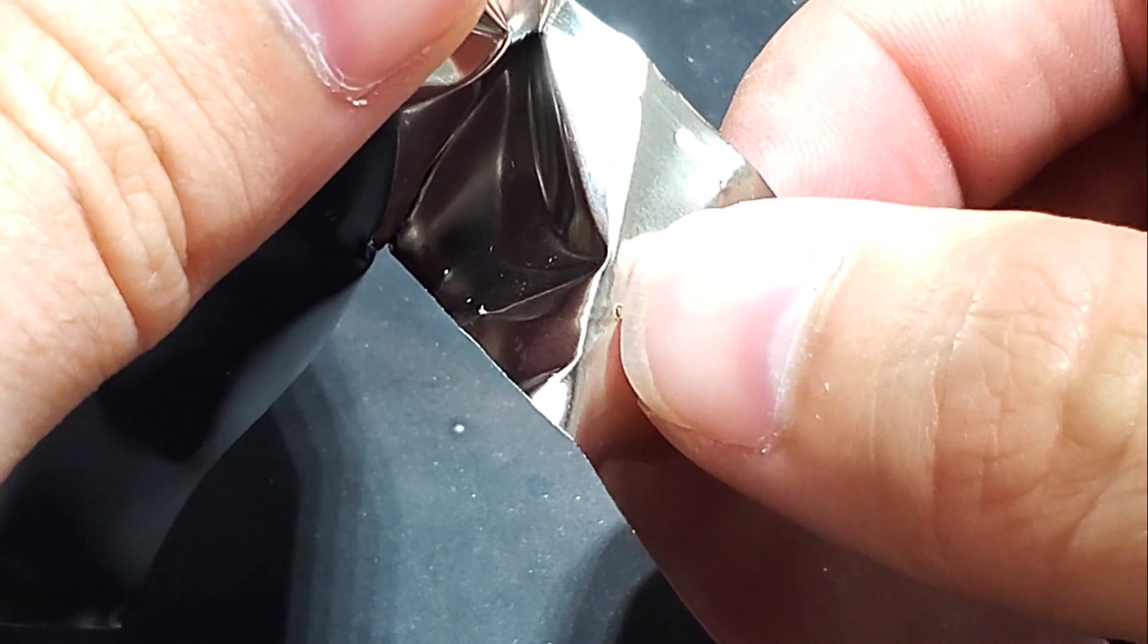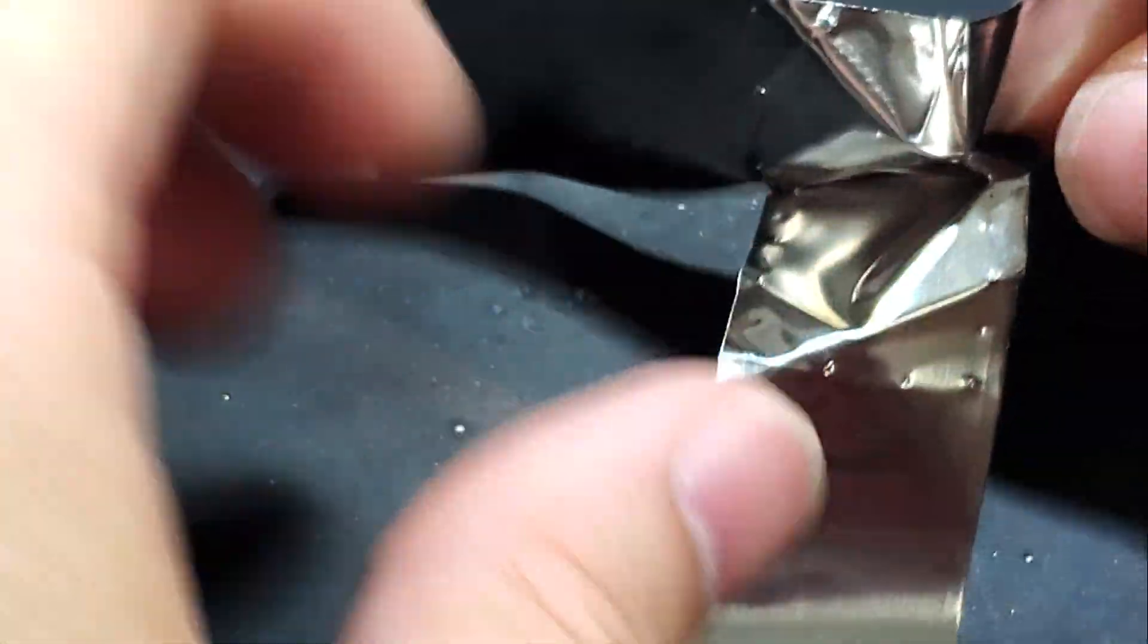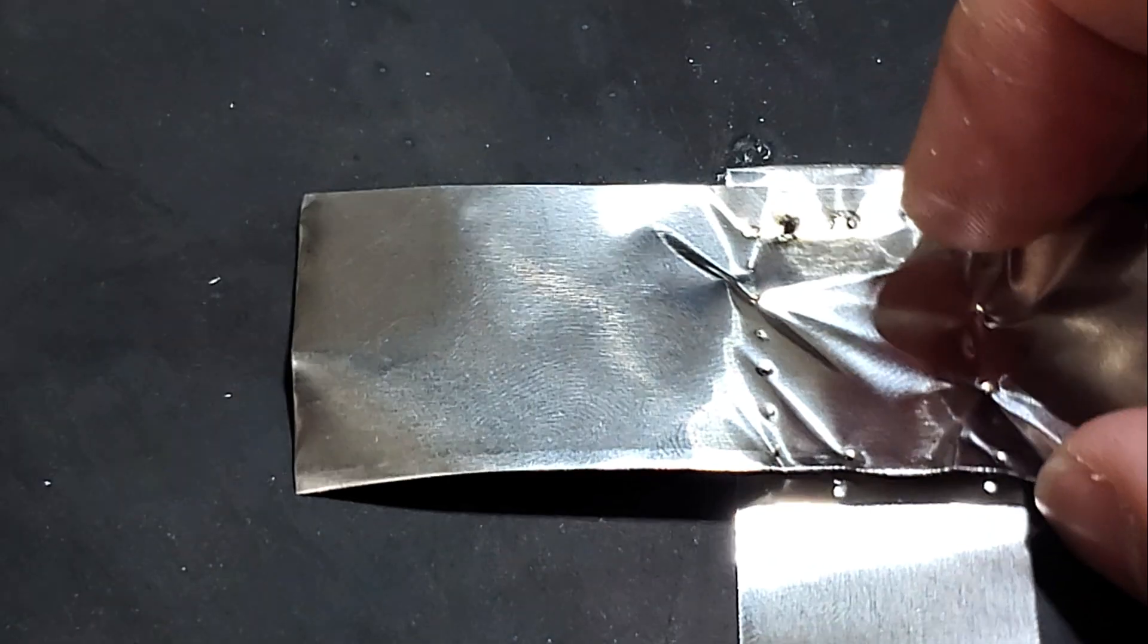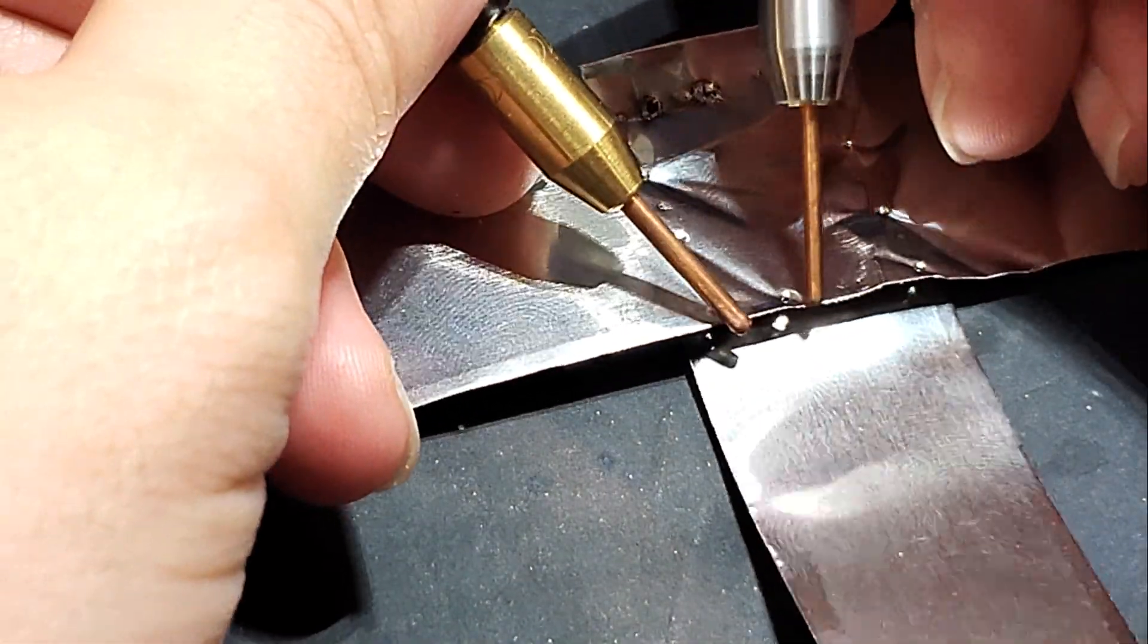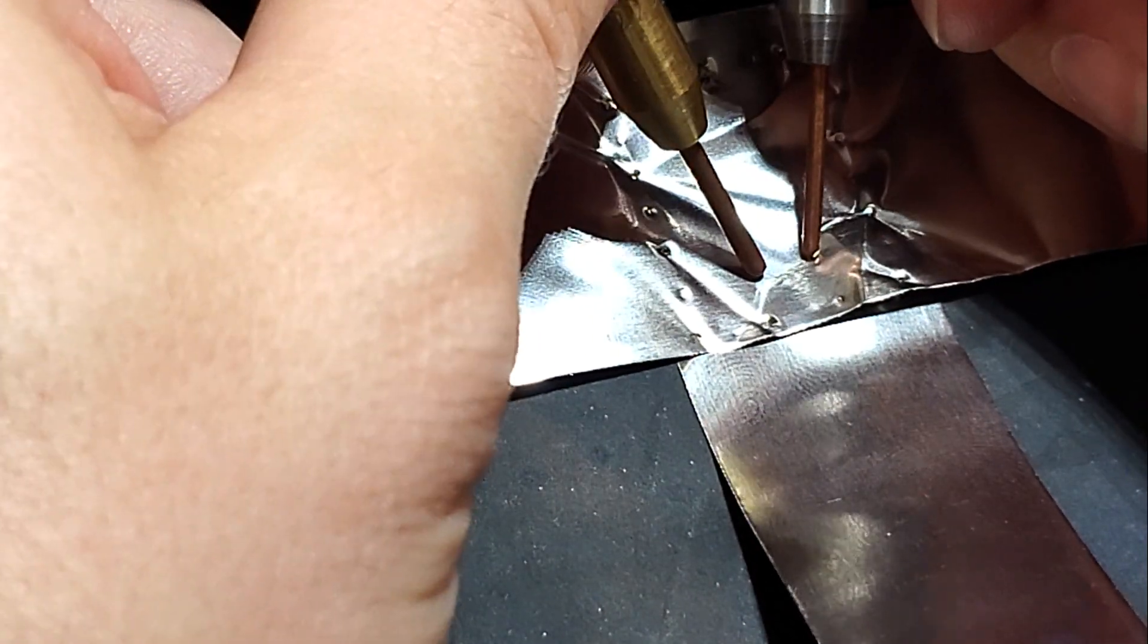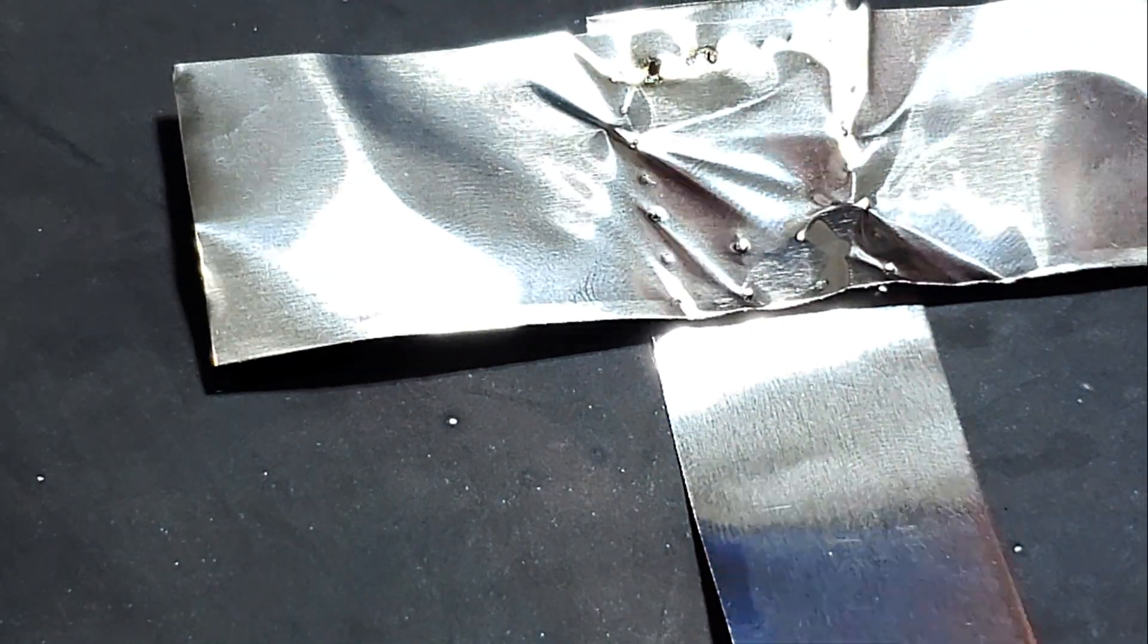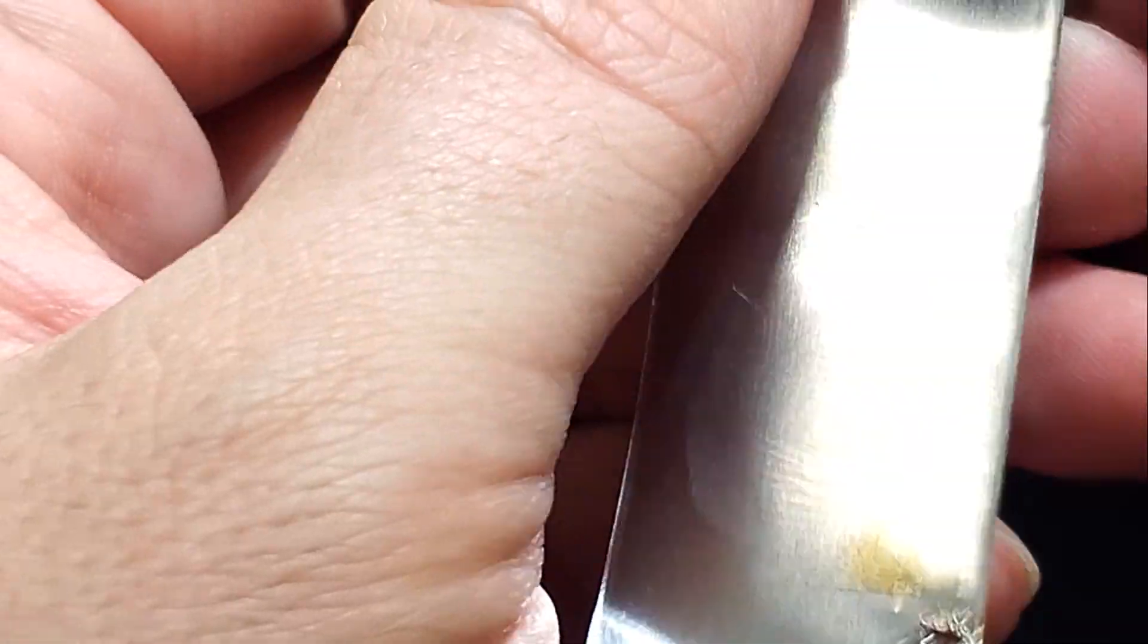Something to note is it looks like we could either turn up our power to get good nuggets on both but the positive terminal seems to be the hotter of the two welds. So let's just do one last weld. Okay. That's correct. So the positive terminal is hotter.